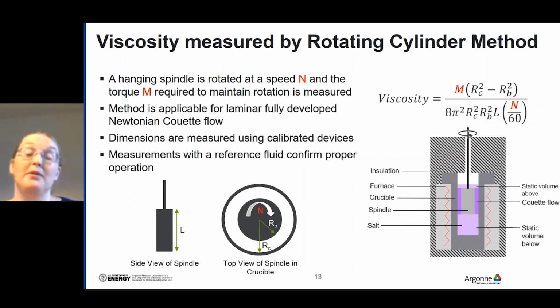Now I'll move on to some viscosity measurements. So this is measured in argon using a rotating cylinder method. The idea here is that we hang a spindle from the viscometer, which rotates it at a certain speed and measures the torque that it requires to maintain that speed. This method is only applicable if you have laminar, fully developed Newtonian Couette flow. So this goes to applicability of the calculation method.